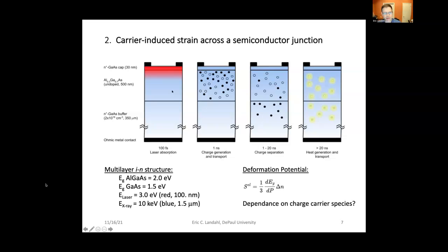And the AlGaAs is fairly opaque to the laser light. The X-rays continue to probe a depth through all of these into the bulk, which is again an N-doped gallium arsenide layer, which is quite thick, 350 microns or more, with again a grounded electrode on the back end.